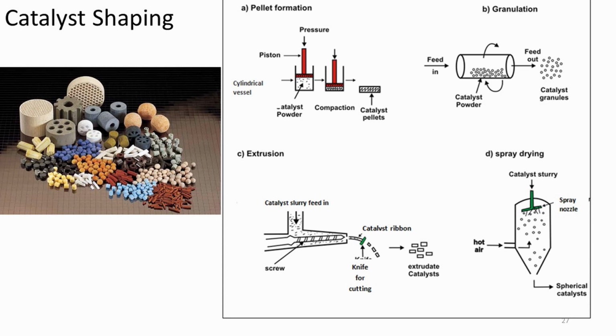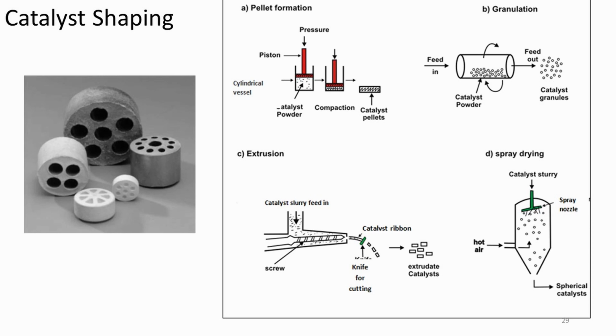What makes the difference between a research catalyst sample and an industrial catalyst? Obviously, industrial catalysts are shaped bodies, with appearance varying from tiny fluidized bed shapes up to large monolithic blocks, and they are manufactured on a large scale. Pelleting is a high pressure agglomeration technique producing particles, usually short cylinders with high shape accuracy. Typically the dry catalyst powder is compressed by applying force up to 80 kN with a punching tool.